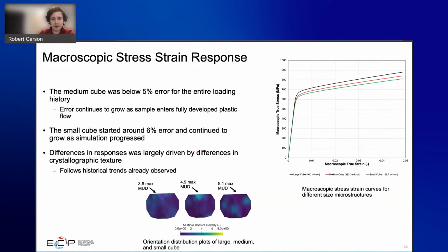So our representative volume should be somewhere between what the medium cube is and the large cube, because we do see the error growing as the sample starts entering fully developed plastic flow. But if you really wanted to, we could potentially get away with the medium cube. The reason I mention that is the small cube didn't start out too well. It started around 6% error at the beginning, and then that error just continued to grow as you got further and further out.